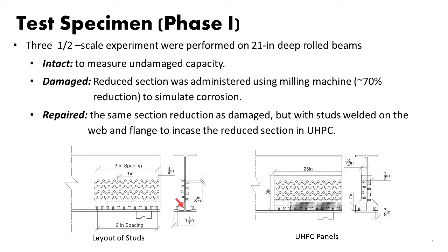For the first phase, we tested three specimens, and one was an intact benchmark rolled girder, 21 inches deep. The second one was damaged, where we introduced corrosion by reducing 70% of the cross-section area of the web and also the bottom flange. You can see here the portion of the web that was reduced, and also the flange. And the third specimen was essentially identical to the second one, but we shot some studs on the intact portion and cast ultra-high performance concrete around that. And we cleared the top portion if there is a diaphragm, although ultra-high performance concrete is flowable enough to go around the diaphragm, and there is no issue with that.